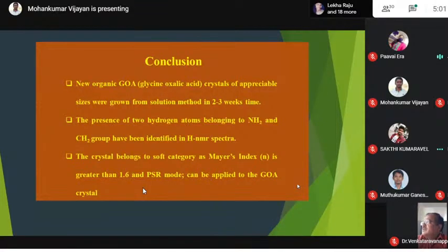Conclusion. New organic GOA crystals of appreciable size were grown from the solution method in 2 to 3 weeks time. The presence of two hydrogen atoms belonging to NH2 and CH2 groups have been identified in the HNMR spectra. The crystal belongs to the soft category as Meyer index n is greater than 1.6, and the PSR model can be applied to GOA crystal.